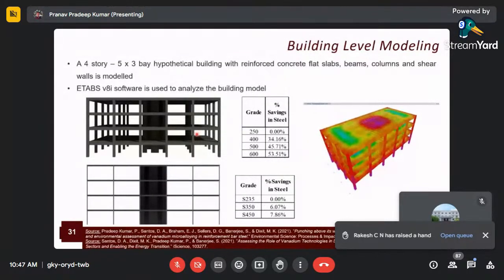And moving to the building level modeling, we modeled a 4-story 5x3 bay hypothetical building with reinforced concrete flat slabs, beams, columns, and shear walls were also modeled. And we only changed the frames to steel frames in order to analyze the steel section building. ETABS software was used to analyze this, and all the standard specifications from Eurocode were used to perform the analysis. And you can see how this translates into percentage savings in steel, where the 250 grade is a mild steel that does not use vanadium, or there's 0% vanadium in that grade of steel, whereas 400, 500, and 600 are high-strength low alloy steels that have some amount of vanadium microalloyed into those steels.